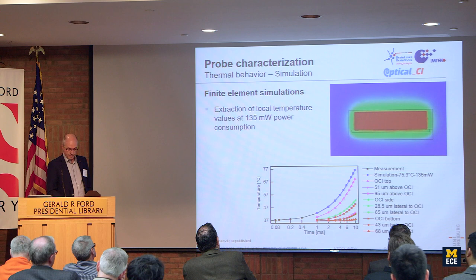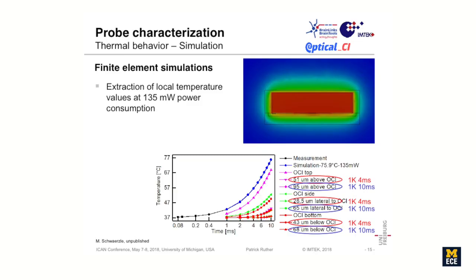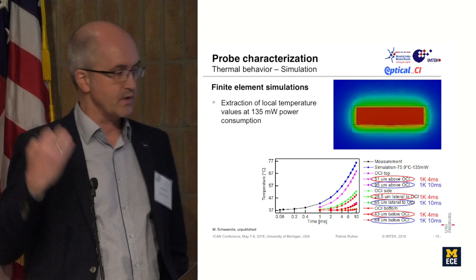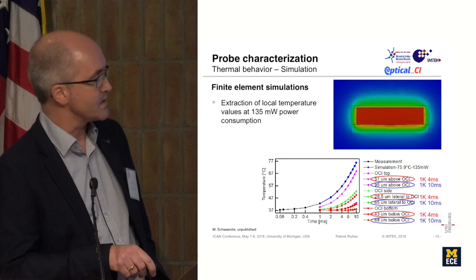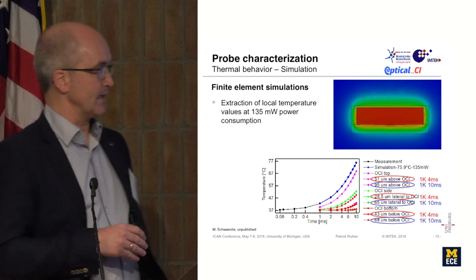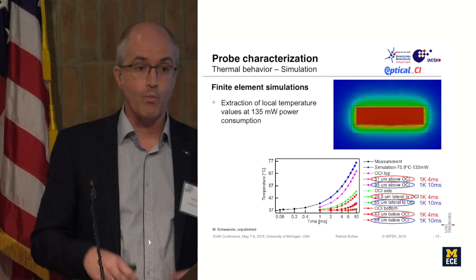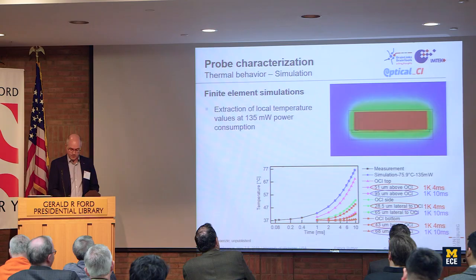And we also looked at different scenarios, in particular, what if we would accept 1 Kelvin of temperature increase for a 4 millisecond long pulse. We clearly see that this increase is reached 51 microns above the probe, and in between the temperature increase is higher. And the same we see here for 10 millisecond long pulses. Here we have to go 95 microns away from our probe to reach this 1 Kelvin limit. So this is something to be taken into account, but please keep in mind 135 milliwatts are applied. We can operate also down here. So this is just for the safety limits.